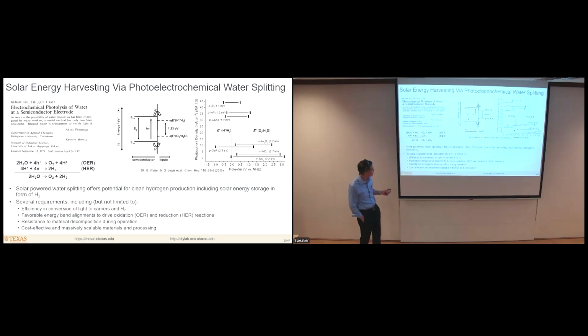You want the energy bands to be properly aligned with the redox potentials. You also want these absorber materials, ideally, to be resistant to decomposition, corrosion, or oxidation in the presence of these water splitting reactions. And that's actually a major issue because materials that are good solar absorbers generally are not stable in solution in the presence of these reactions. Materials that are stable are usually wide bandgap metal oxides, but those are very poor solar absorbers. So there's already this conflict between what's required for efficient solar absorption and stability.